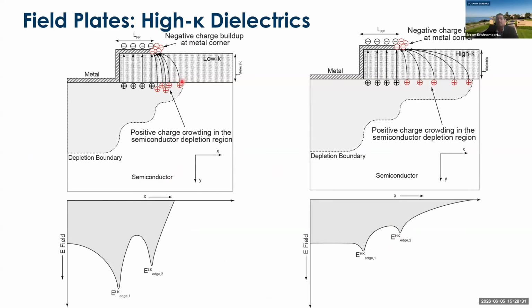So to further push this, we've been exploring using high permittivity dielectrics. So basically, we can add dielectrics which have a much higher dielectric constant. And what this lets us do is it further helps us in spreading out the depletion region, and the electric field can be lowered by using a high permittivity dielectric instead of a low permittivity dielectric for the field plate oxide.